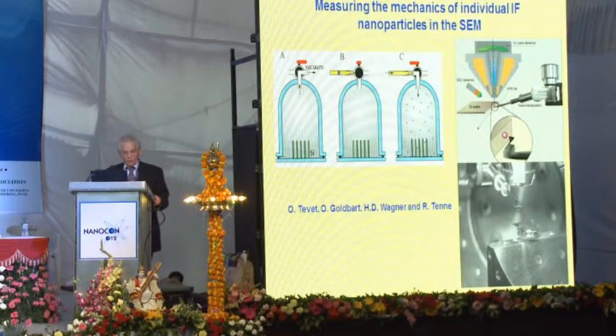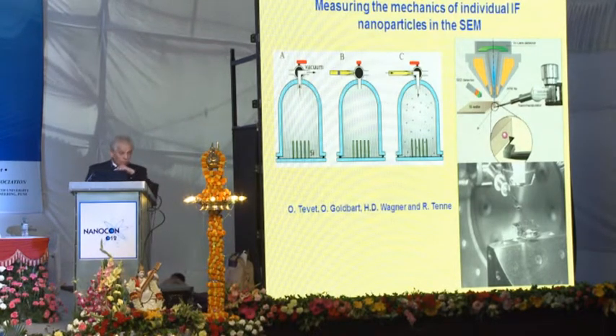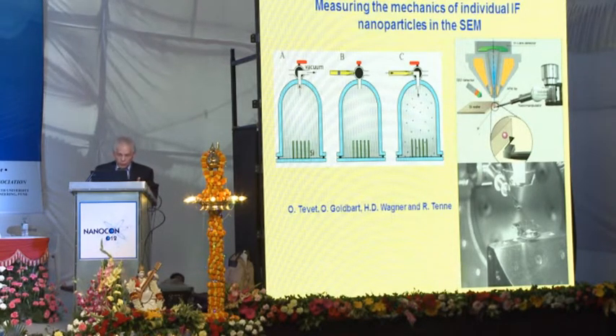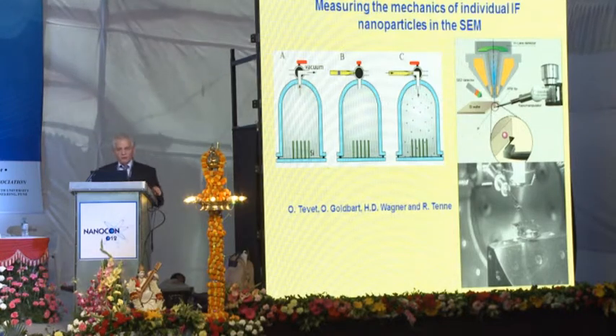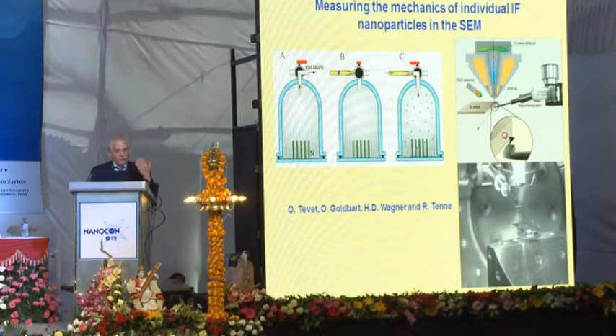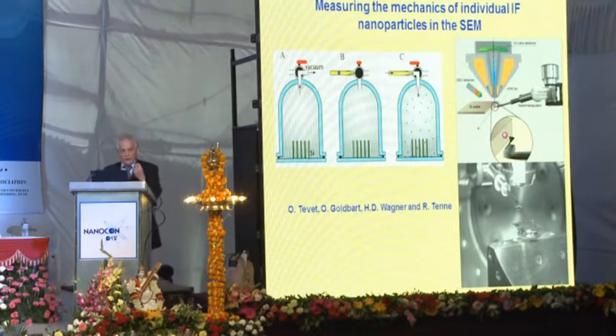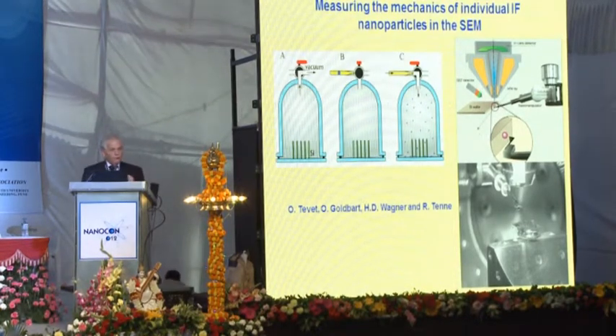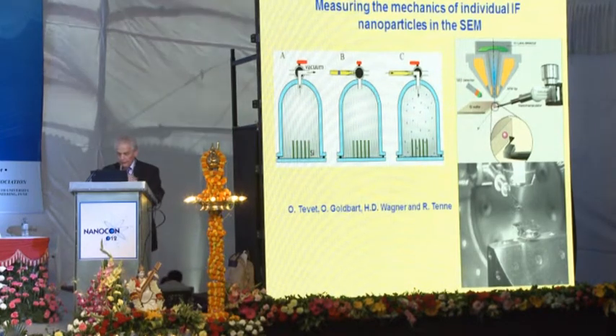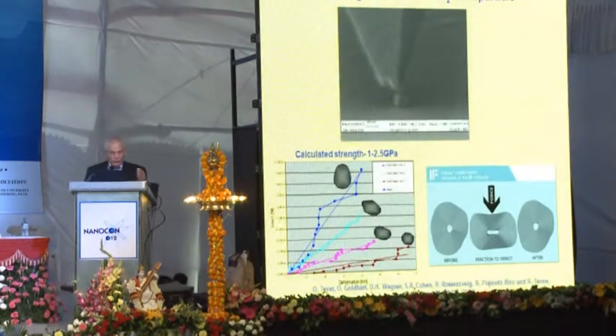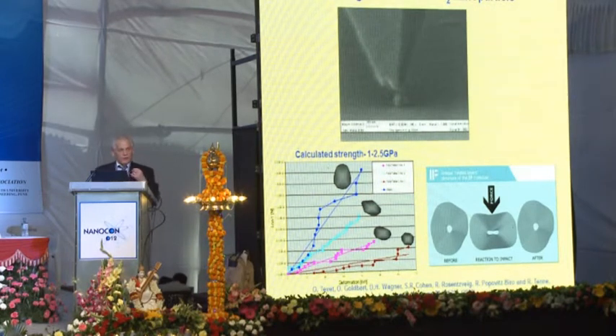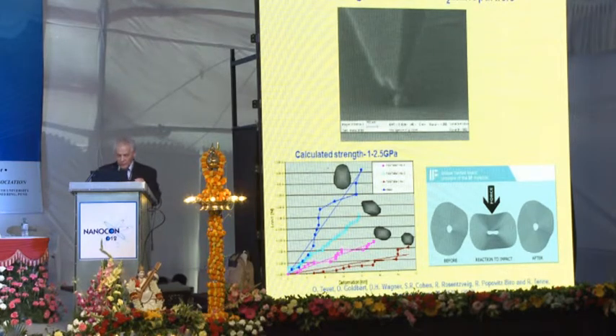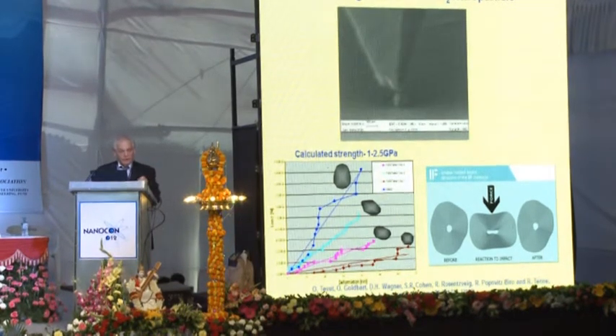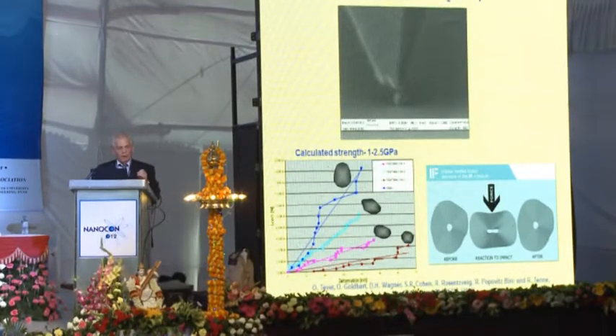And indeed, we showed that they can withstand pressure of about 1 to 2.5 gigapascal under both loading and shearing before they start to fail. And this is very important for lubrication because this is the first description of rolling friction that exists in nature or in science. So we have demonstrated that these nanoparticles are very robust and at the same time they roll under very high pressure and they can provide very effective means of lubrication under boundary lubrication conditions.